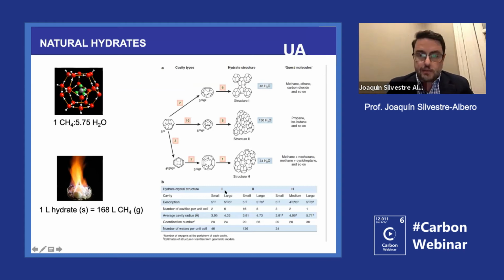So if you see the table that I put here, structure number 1 is the one that you get when you put methane. And this structure is made of small and large cavities. And as you can see, the size of the cavity is 3.95 angstrom and 4.33. So this is the perfect size to allocate the small molecules. If you are working with propane or isobutane, you will get structure number 2, which is a bit more complex. And there is also structure H, which is a combination of small, medium, and large cages. And this is only possible when you combine hydrocarbons, like methane with cyclopentane or whatever.